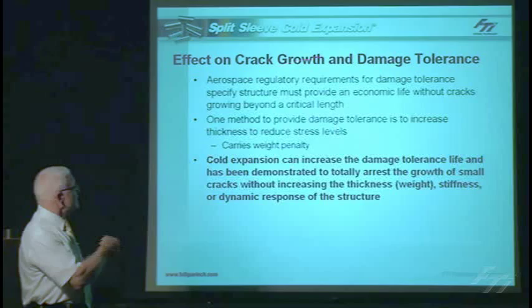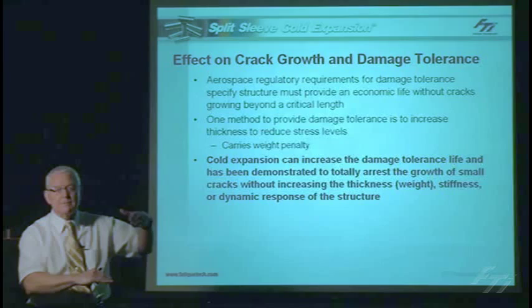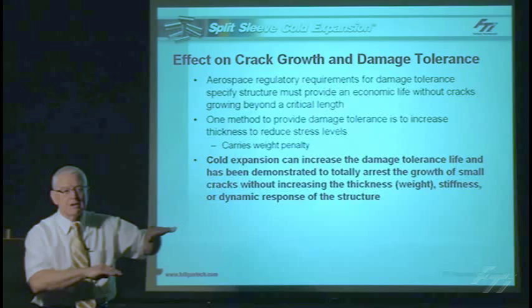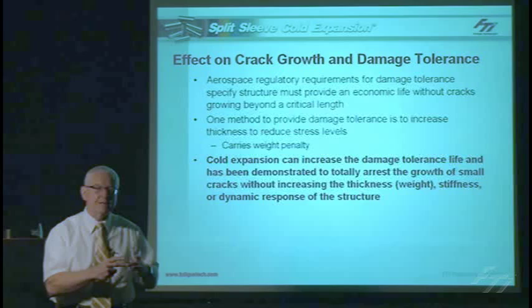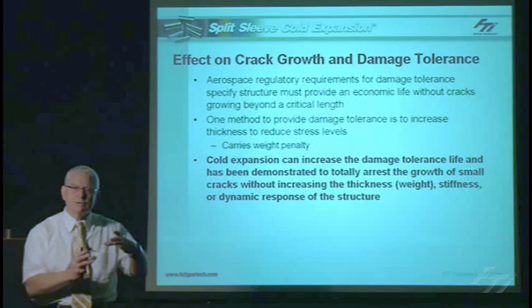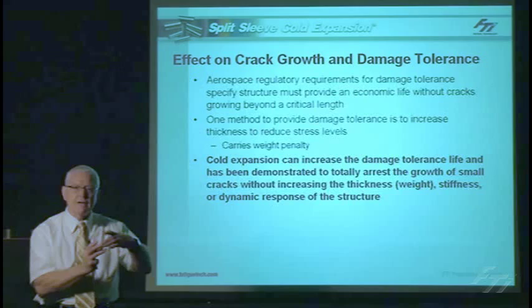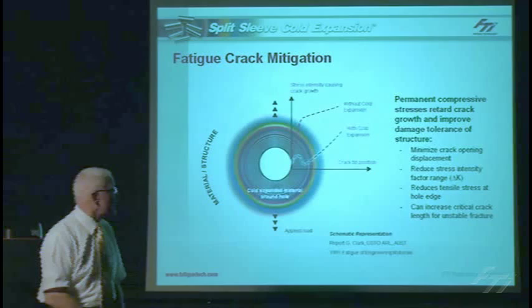To stop those cracks growing, we can increase the thickness or put a doubler on there, but that adds weight and changes the stiffness and dynamic response of the structure. But if we cold work that existing structure and put in that residual compressive stress, even if you have a small pre-existing crack in the hole, that residual compressive stress will keep the crack closed and in most cases prevent further growth, as long as the stress levels don't exceed what the loads need to open the crack.